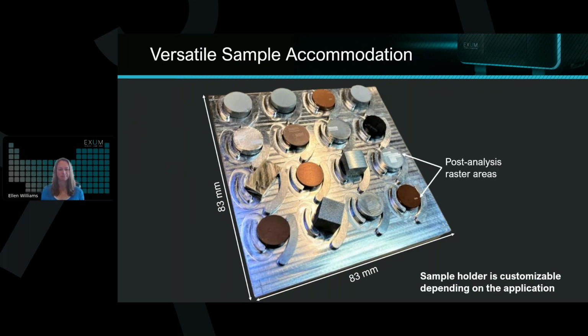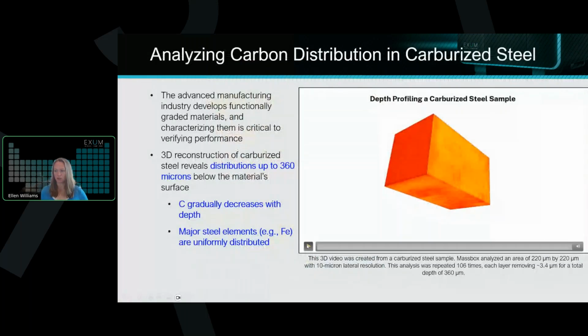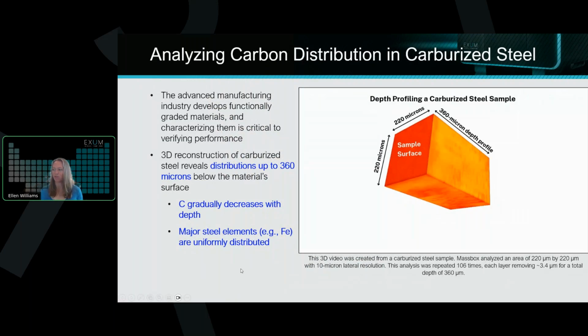Thank you. Speaking about the ablation, how much material is removed by Massbox ablation process? Yeah, so it is material dependent, and I mentioned there is some flexibility in terms of the user being able to change the laser power. So we have experience doing thin film analysis where we're removing on the order of tens of nanometers per layer. Then I also alluded to this study where we actually profiled through 360 microns of a carburized steel sample.